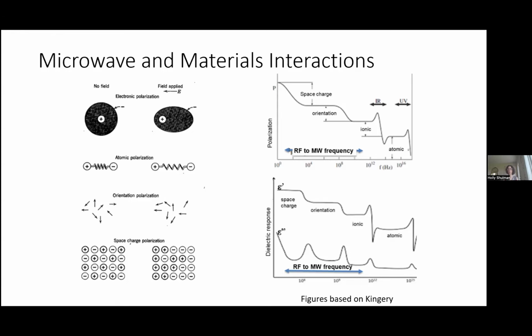It's like they're frozen. And there is an analogy with temperature and frequency. So at higher temperatures, you put more energy in, you warm things up, you're better able to flip polarization to align with the field, right? But then as you go to colder temperatures, you might freeze in those polarizations, and then they don't add to what we call the dielectric loss. And the dielectric loss, I'm actually going to show that on the next slide.